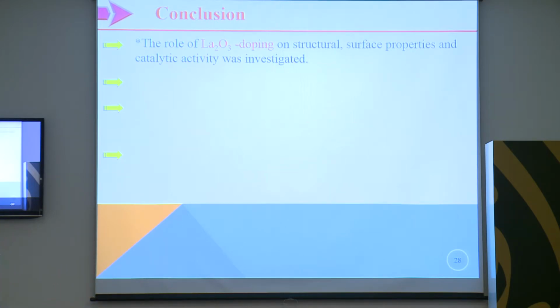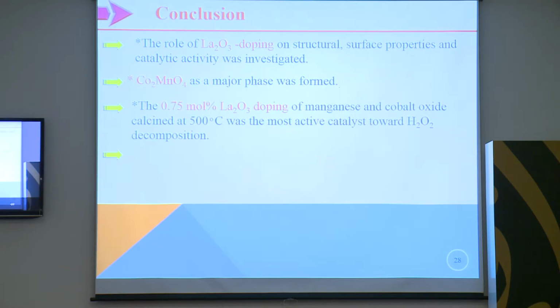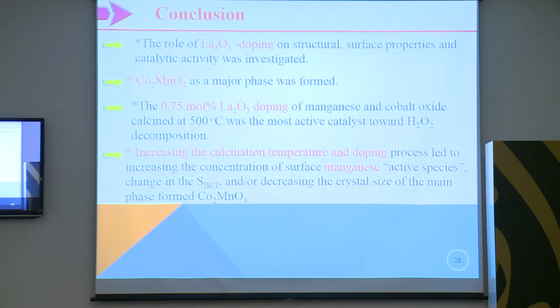The conclusion for the article: the role of lanthanum oxide doping on structural, surface properties and the catalytic activity was investigated. Cobalt manganese oxide (Co2MnO4) as the main phase was formed. 0.75% lanthanum oxide doping on manganese and cobalt oxide calcined at 500 degrees was the most active catalyst toward hydrogen peroxide decomposition. Increasing calcination temperature and the doping process led to increasing the concentration of surface manganese as active species and a change in surface area or decreasing the crystal size of the main phase.